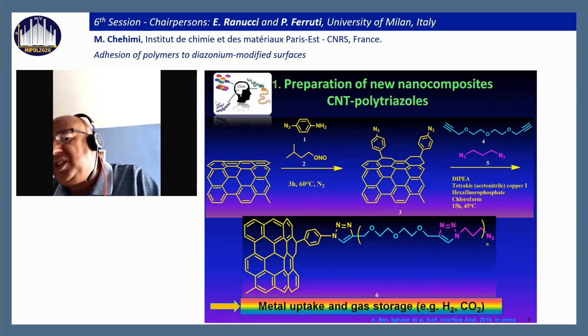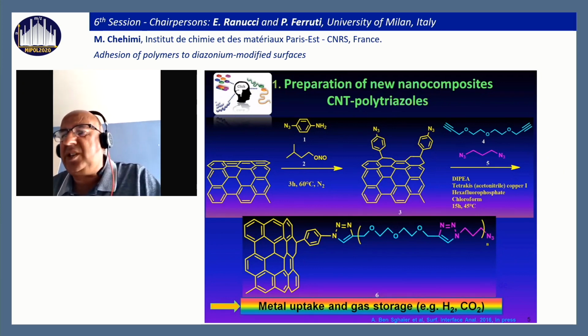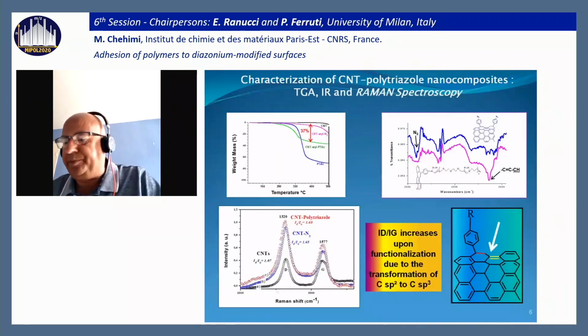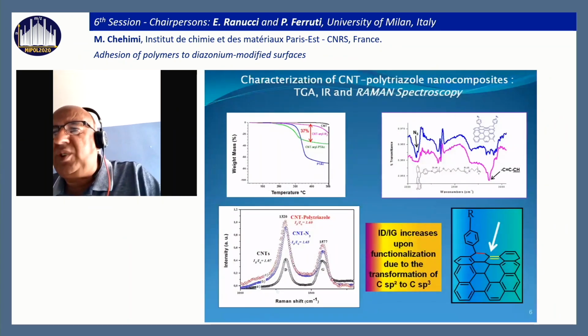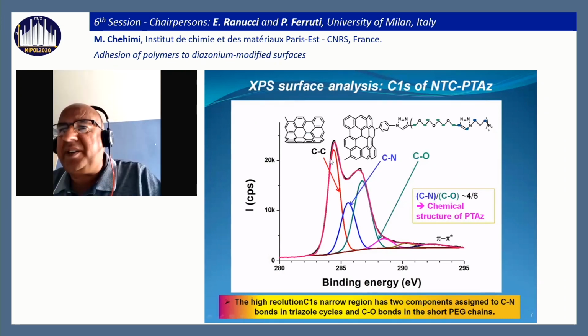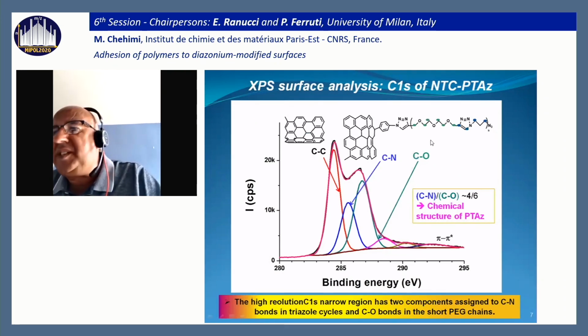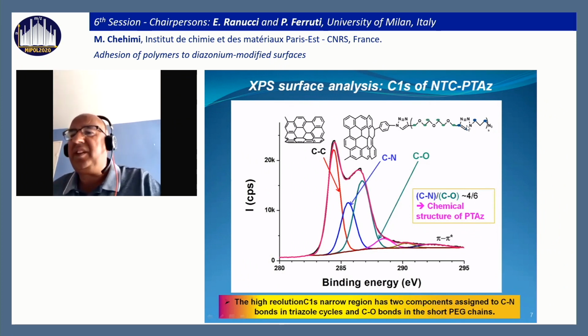It could be, we didn't try to find some applications. We published this in a small paper in 2016. I just want to show you the XPS part. This is the contribution of the carbon nanotube, and you see here the different contributions of these functional groups: the ethylene glycol part, the CN bonds from the triazole, and from this part of the polymer chain.